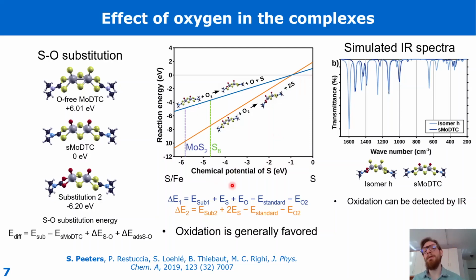Here, the chemical potentials range from a very unfavorable situation of isolated sulfur atoms, and on the left we have a very favorable situation, which is sulfur atoms adsorbed on iron. And here the vertical line is our target material, MoS2.